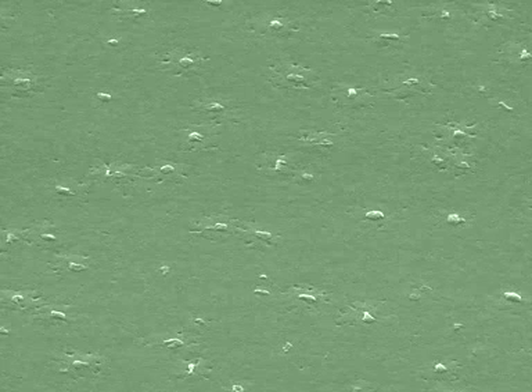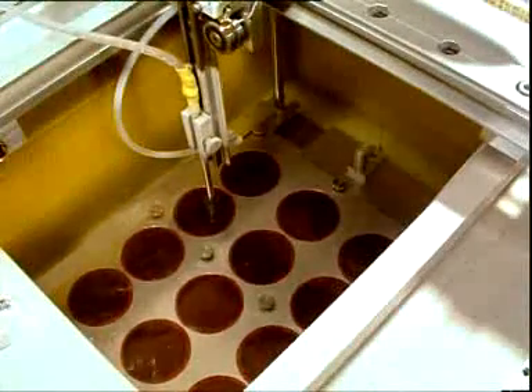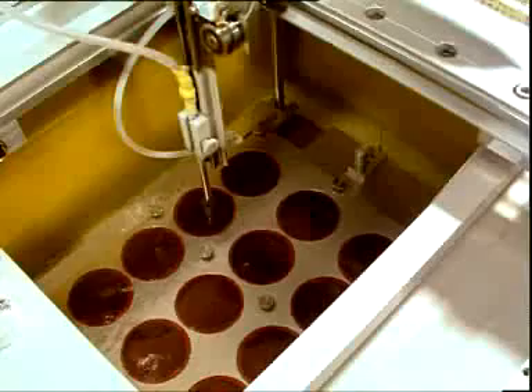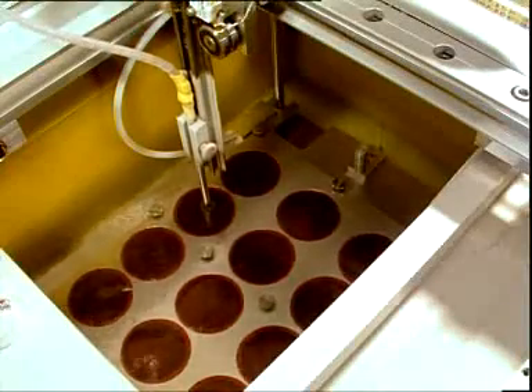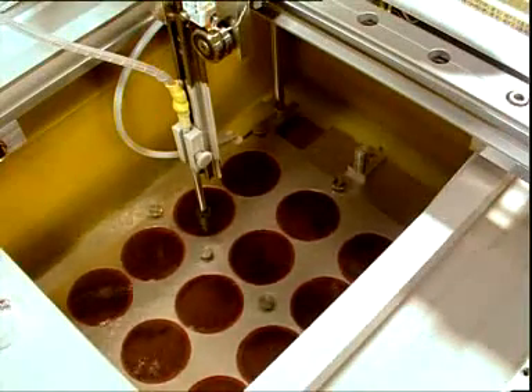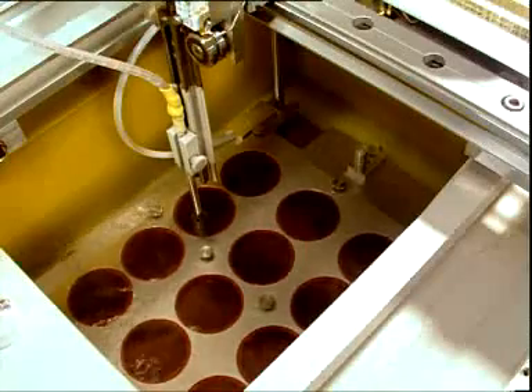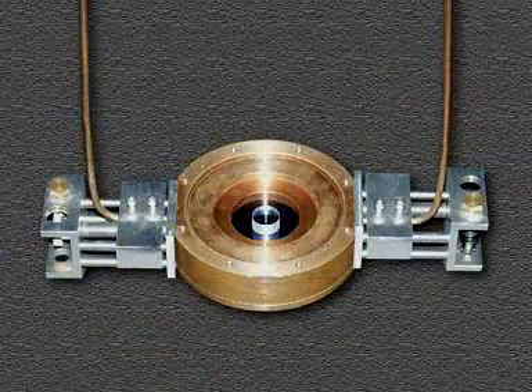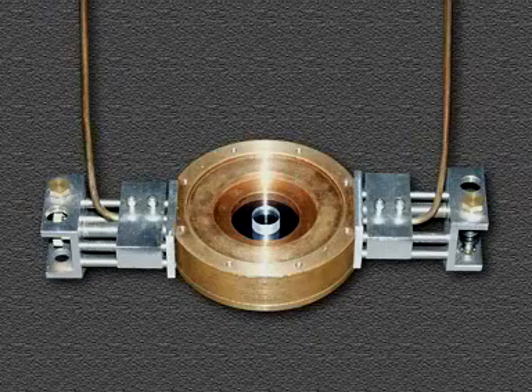Films can be fabricated custom designed for various applications, from extremely smooth for multi-layers to rugged with a high density of pinning centers for microwave applications. Another standard inspection is the mapping of the uniformity of the critical current density by a cryoscan. Measurements of the transition temperature and the microwave surface resistance are performed as spot checks.